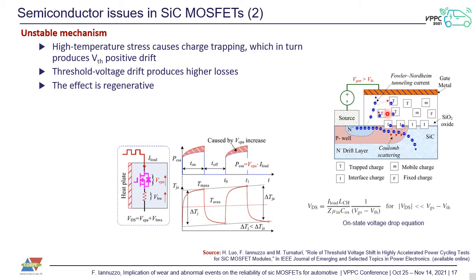In this case, you're adding additional negative charge to the gate, which ends up increasing the threshold voltage. Now, if you look at this equation, which is the very basic equation of on-state voltage drop of MOSFETs, if you increase the threshold voltage, this number at the denominator decreases. But being at the denominator, the on-state voltage drop increases in turn. So because of this drifting phenomenon, the on-state voltage drop increases, and this increases the power dissipation at a given current level. Schematically, during power cycling, with the temperature swing constant, the average and the maximum temperature drift up, as in this case, and of course the power losses in the top figure here increase as well.